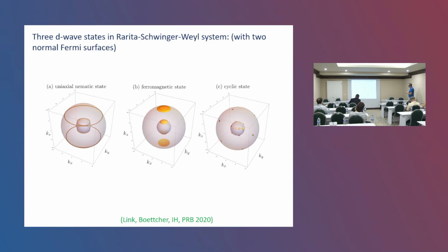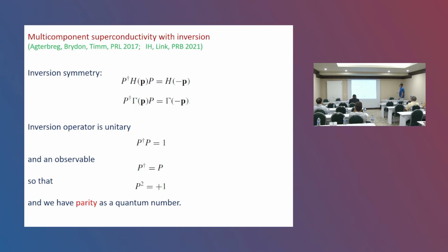Thing to notice about these surfaces, these surfaces are so small that you would think they're just actually points. They're much smaller than the original Fermi surface. So there is actually a gain in energy still by opening a superconducting gap, right? Because most of the original Fermi surface is actually gapped. But the things that are not gapped are still surfaces. Right? So if you look at low energy penetration depth or specific heat, you would actually see different power laws than if you had, for example, this situation here. So this is one way to think about it.